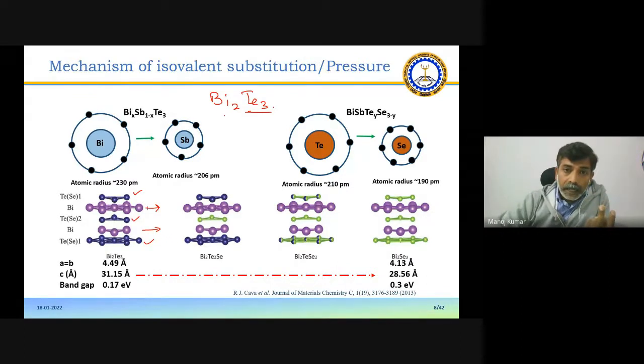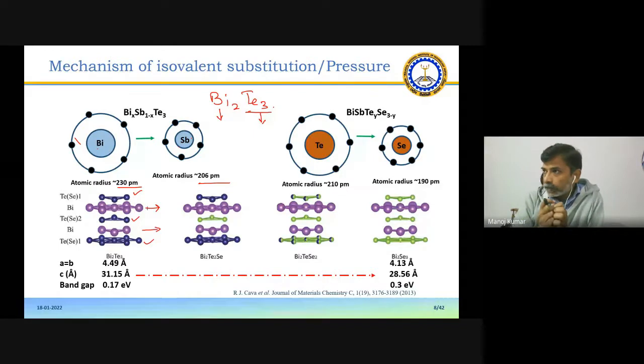So two layers of bismuth and three layers of tellurium. We can actually replace both these positions. So if we replace Bi with antimony, Bi has a larger atomic radius compared to antimony, and this will induce a sort of volume contraction in the material. In the same way, if we replace tellurium with selenium, there also we can compress it further, okay?